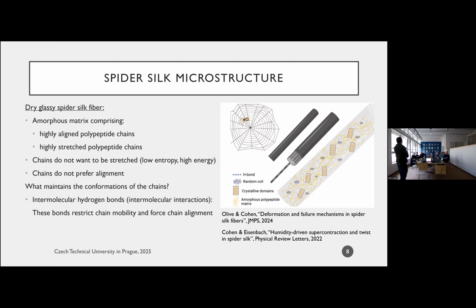Now, if you recall from polymer physics, chains do not like to be stretched. A chain never wants to be stretched. Being stretched for a chain is like being in a low entropy or high energy state. So if I had just a standard polymer chain and I were to put it on the table, it would immediately contract because it wants to maximize entropy or, alternatively, minimize free energy. In addition, in a network, chains never want to be aligned. If there's no preference, no bias, there's no reason for the chains to be aligned. Yet this microstructure still occupies this configuration, which is energetically unfavorable. So how does this happen?